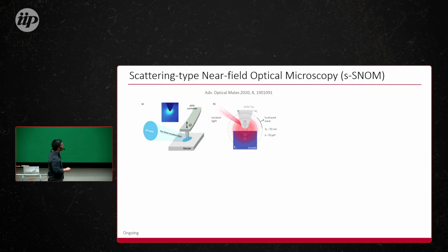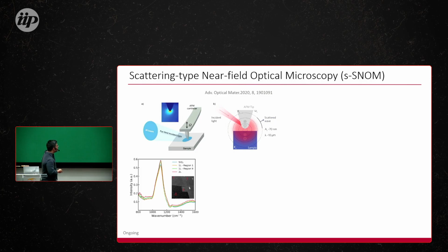And we have amplification here of the electromagnetic field because of the tip. The one we use is gold, and I think the resolution is about 20 or 25 nanometers, I do not recall properly. And what we did was to collect an infrared signal, that's all. So this is a synchrotron measurement. This is the peak that we are actually measuring. This peak over here is because of the silicon substrate. So we are using silicon.